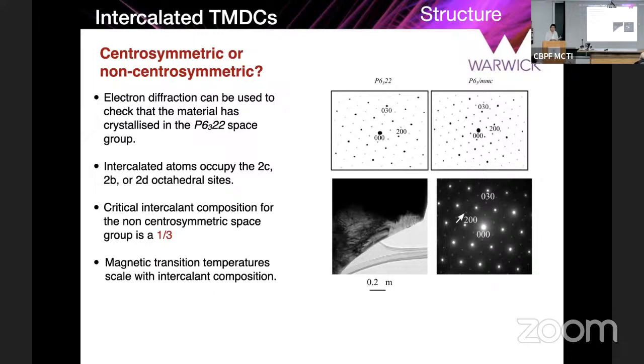The most straightforward method would be to do single crystal X-ray diffraction. But it turns out that it's not very clear from single crystal X-ray diffraction to distinguish between these two space groups, which are very, very closely aligned. So we use the TEM, the microscopy technique, to look at the electron diffraction in these. And you can tell by the relative intensities of the 030 and the 200 spots here whether it's non-centrosymmetric or centrosymmetric. So ideally, we are aiming for a critical composition of one-third here.